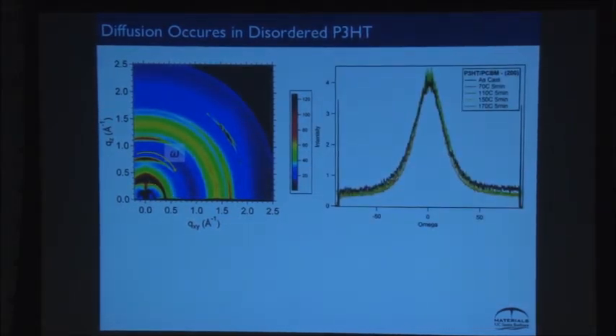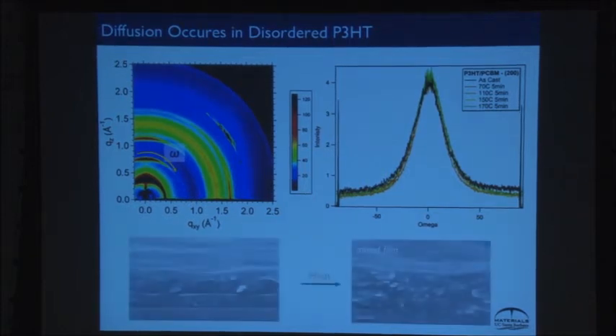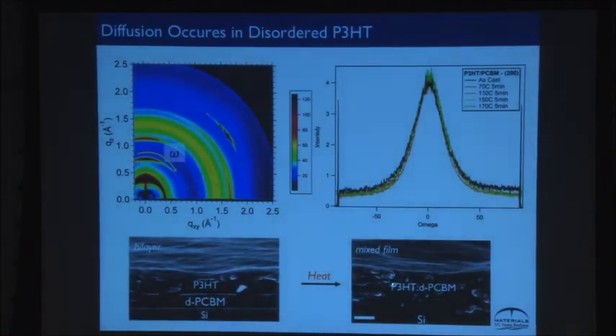And I would have thought if I had this very dramatic change, if I go from something that's flat to something that's fully mixed, you might imagine if I have physical crystallites, they're going to move. You might imagine something ought to happen. Nothing happened. We don't get any change in the orientational distribution. And so that says that some of this material in the P3HT is amorphous, and we think that we saw this right away, and we decided that the fullerene had to be going through the amorphous fraction of this polymer.